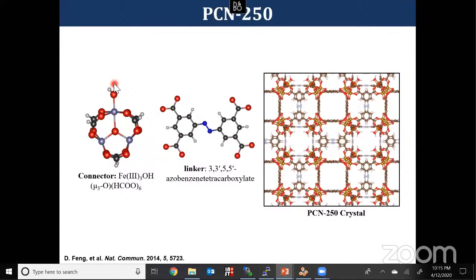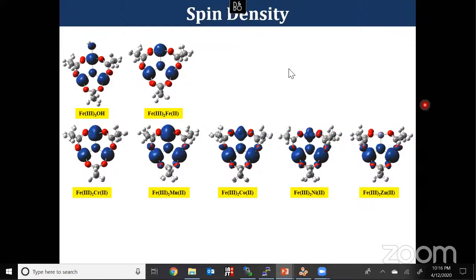And one more interesting thing is that if it forms a heterometallic center, we can substitute or replace the 2+ metal with various metal cations with a 2+ oxidation state. There are experimental reports available of PCN-250 clusters substituted with various divalent transition metals. But in this work, we replaced this Fe2+, this OH, with chromium, manganese, cobalt, nickel, as well as zinc 2+. So we created various heterometal substituted moieties.